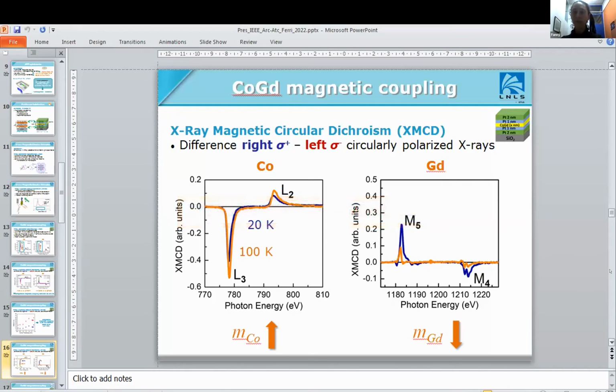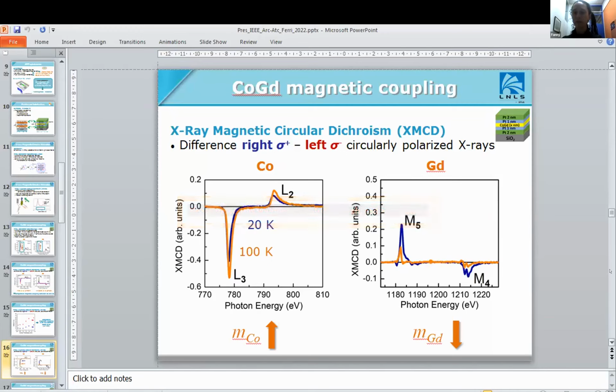We also used this technique to know, as a function of temperature, what was occurring for the magnetic moment of each element. And so we did some measurements at 20 K and at 100 K. For the cobalt, you can see that when we increase the temperature, passing from 20 to 100 Kelvin, the XMCD signal increases, and so the magnetic moment of cobalt increases with the temperature. While for the gadolinium, we have the inverse. When we increase the temperature, we have a decrease of the XMCD signal. So when we vary the temperature, the moment of the cobalt increases and the moment of the gadolinium decreases.